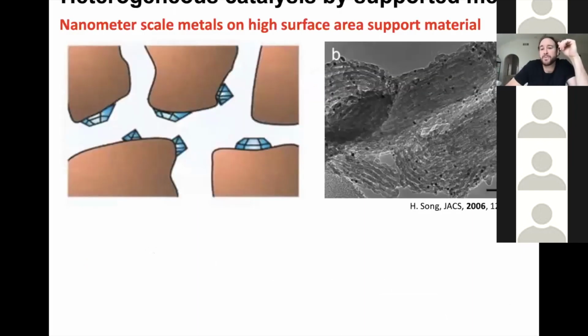And when you think about a supported metal catalyst, you can think about it in lots of different ways. But the easiest way for me to think about it is technologically, when something is put into a reactor as a supported metal catalyst, you usually have a domain that looks like this. That's some sort of oxide material, most typically. Usually these are thermally stable oxides like silica, alumina, sometimes things like titania, sometimes zeolites, which are silica aluminates. And these are often thermally stable, mechanically stable, and extremely high surface area materials. So oftentimes somewhere between 100 or 1,000 meters squared of internal surface area per gram of material.